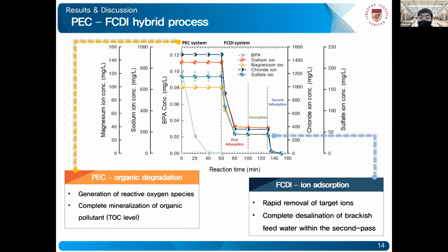Now, the subsequent FCDI process led to the rapid decrease in the target ionic concentration, with removal efficiency averaging 80% in the first adsorption process. Now, after a desorption process to regenerate saturated activated carbon electrodes, operation of the second pass FCDI system obtained complete deionization of the permeate stream.